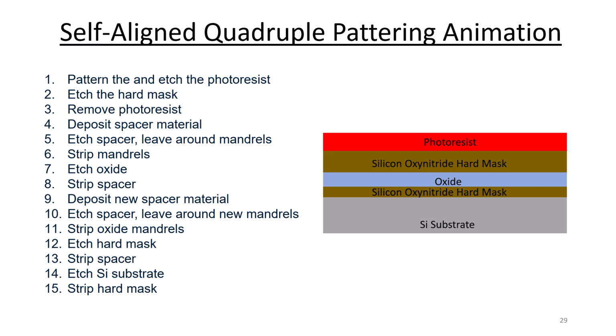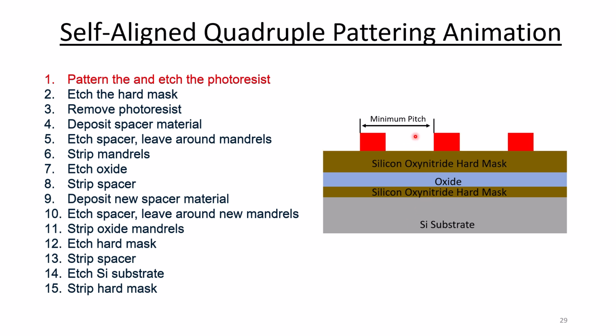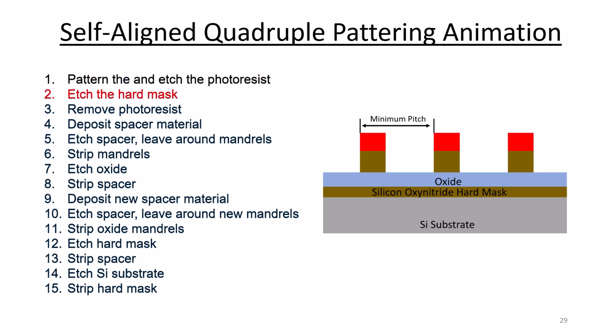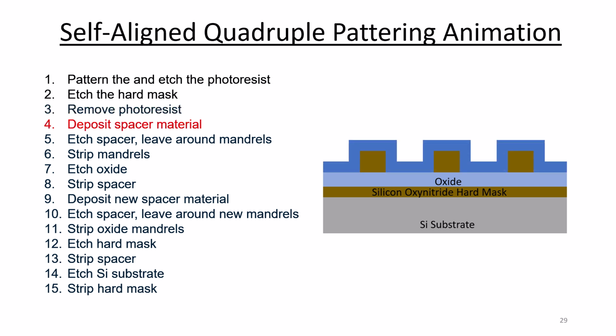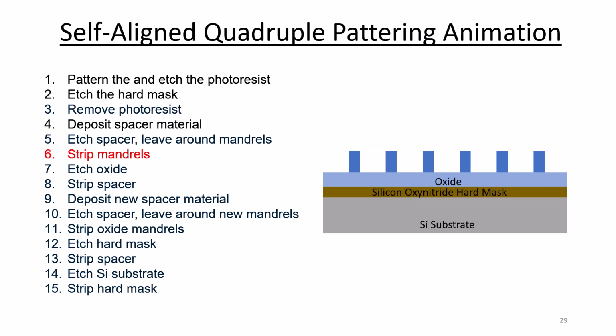Now I wanted to go through some animation to kind of show you how this works. So we're going to do patterning and etching of the photoresist first. And once again, we start out with minimum pitch. The next step is to etch the hard mask. Now we remove the photoresist. Now we deposit the spacer material. Now we etch the spacer material, just leaving it around the mandrels. Next, we strip out the mandrels themselves. Now we etch the oxide below the spacer material.